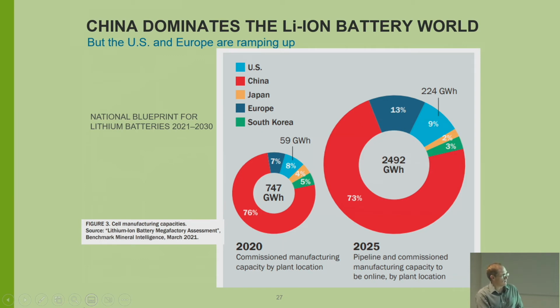But the rest of the world, you look in Europe too, they're building gigawatt-hour factories too. So there's a huge push looking for more lithium, more cobalt, more nickel, all for EVs. Well, I should say EVs, but lithium-ion in general, grid energy storage as well. So the whole lithium-ion technology is not going away. It's well established and growing by the billions every year. Okay, and if you notice, China actually starts to lose, from 76% they go down to 73%, but they're still growing greatly if you look at the size of those two numbers.